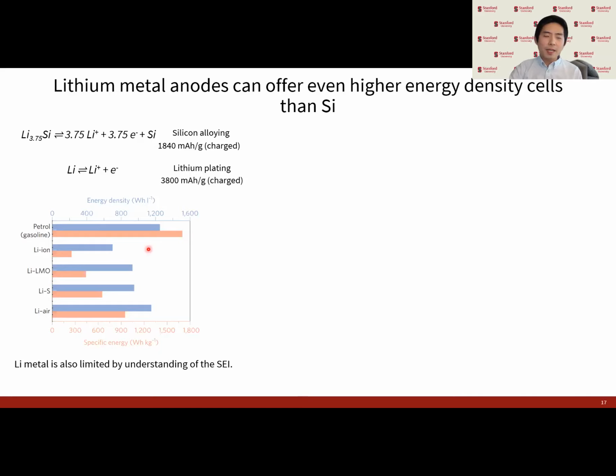And if we can make lithium metal work, we can start to replace these graphite and silicon anodes to push the classic transition metal oxide chemistry to even higher energy densities. But it also opens the door for new cell chemistries, such as lithium sulfur and lithium air, that don't have lithium in the cathode. And these new chemistries can potentially start to approach the energy densities of gasoline. But similar to silicon, lithium metal implementation is limited by the understanding of the SEI.